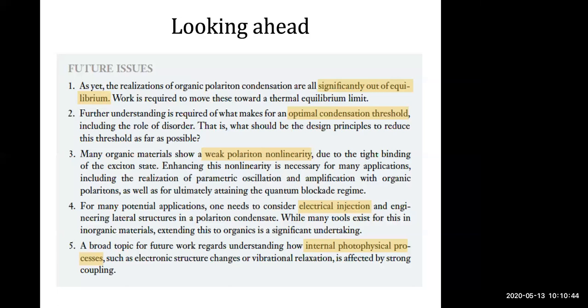But just directly pumping S1, we're certainly not in a regime where we can efficiently populate S2, except for a small caveat: we do have bimolecular annihilation, and that can involve some quick excitation to S2 followed by very fast internal conversion, which leads to the loss of some of these excitons. So in that sense, it's a loss process. Okay, thank you.